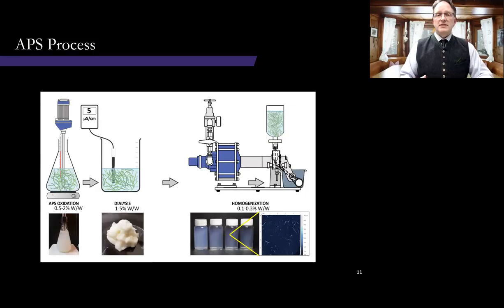So in our process to oxidize using ammonium persulfate, it starts with pulped fiber. And we place that in a continuously stirred temperature-controlled reactor, also known as an Erlenmeyer flask in our case. And the reason for that is we wanted to make sure that any potential reactions that could scavenge ammonium persulfate, such as reactions with metals or chloride ions, were controlled and reduced. And if you look at this lower left-hand image here, that's a photograph of the actual reaction and process.